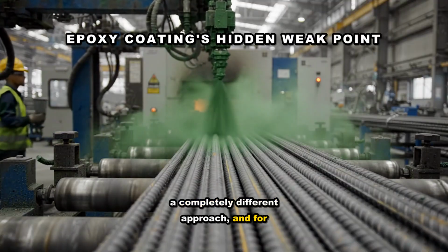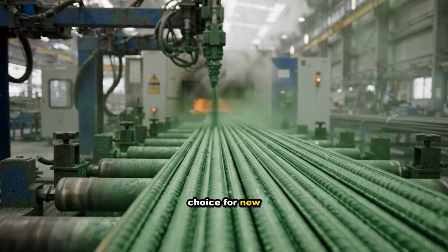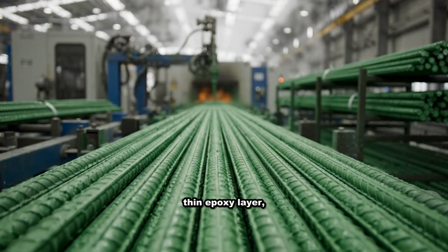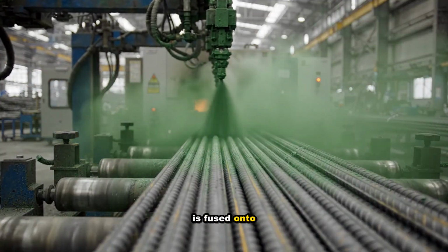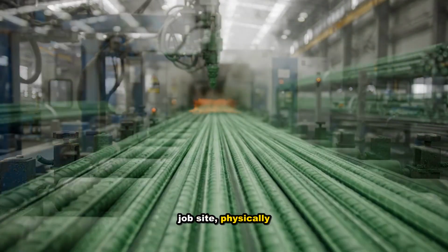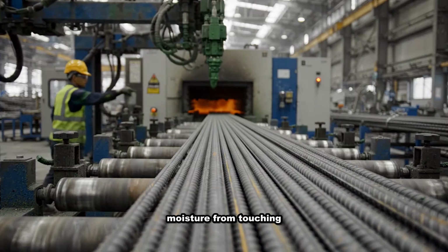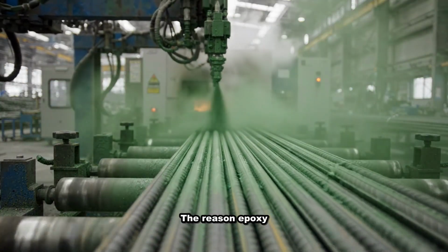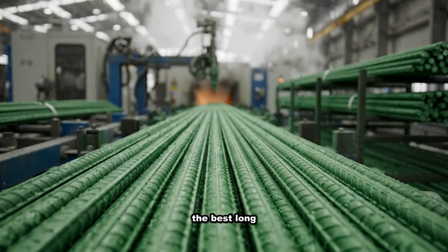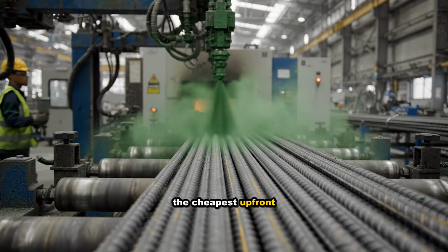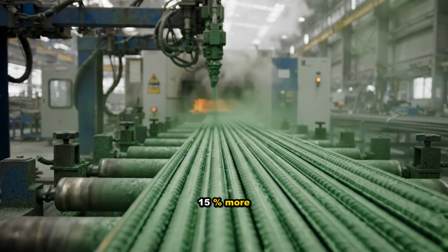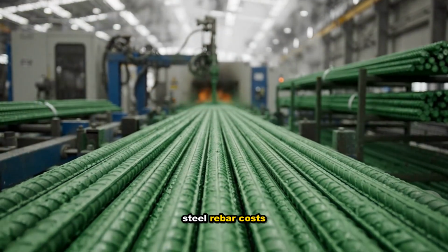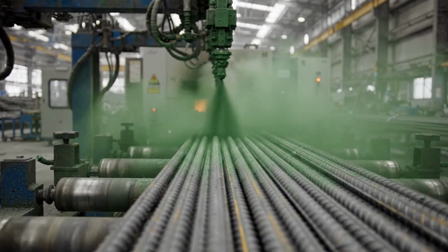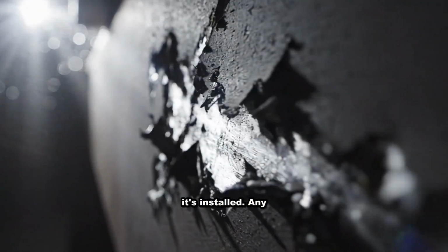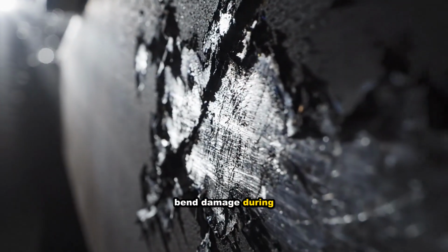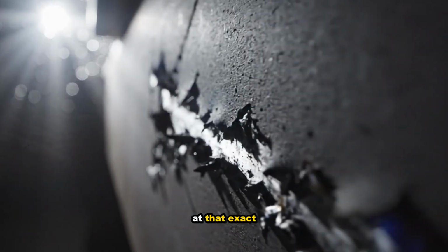Epoxy coating took a completely different approach, and for 30 years it was the default choice for new bridge decks. A thin epoxy layer, roughly 7 to 12 mils thick, is fused onto rebar in a factory before it ever reaches the job site, physically blocking chloride and moisture from touching the steel surface. The reason epoxy-coated rebar became standard was not that it was the best long-term solution. It's that it was the cheapest upfront solution, costing maybe 15% more than plain black bar, while stainless steel rebar costs 4 to 8 times as much. But epoxy coating has a flaw baked into how it's installed. Any nick, scratch, or bend damage during transport and placement exposes bare steel at that exact point.